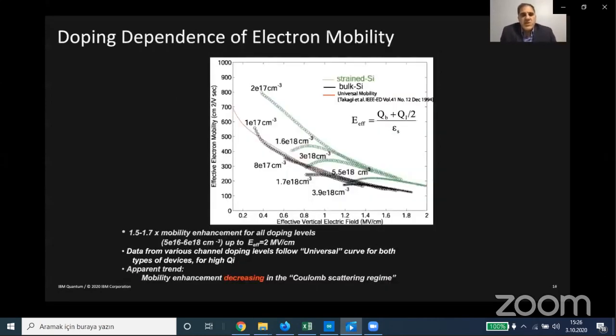Shown here is the resulting characterization of the electron mobility as a function of effective vertical field. As can be seen here, the strain data in green versus the unstrained control shows a boost in the mobility for all the doping concentrations in this study. The amount of boost is around 1.5 to 1.7x.